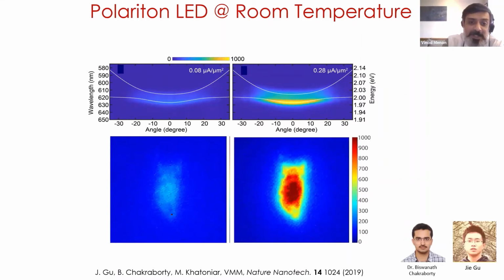So here is the flake. This is my flake in this device, or the region that is actually overlapping with all the layers. Just to give a perspective, this is about 2 micrometers, and this is about 5 microns in length. So that's the area that I'm looking at. It's not a large device, but nevertheless, you can see that at low current density versus high current density, the system lights up very bright.